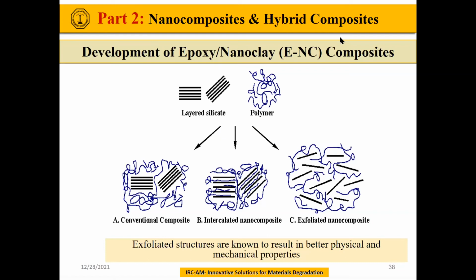In two or three projects that we had, we looked at a number of mixing techniques, types of polymers, and types of clays, and we looked at how we can get the best clay dispersion and distribution. We looked at how to optimize the degassing and curing process. The materials we used were not only epoxy, we also used polyester. We looked at 3 nanoclays, 3 Cloisites, and 3 Nanomers, 6 types. We used high shear mixing and ultrasonication, coupled together or each by itself. And we used the IPDA curing agent, and we worked on degassing and curing of the materials.